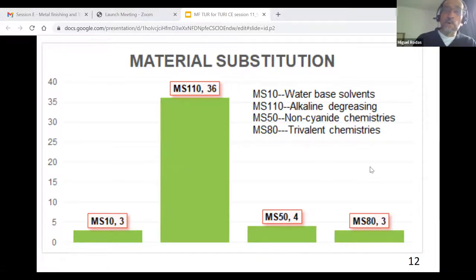And here is what I found on material substitution. 36 facilities are implementing a jump to use water-based alkaline degreasing. So they are no longer using organic solvents, but now they're using alkaline degreasing. MS-10, we find 3 facilities only using water-based solvents, and MS-50 is 4 facilities using non-cyanide chemistries, and the code is the code we use for pollution prevention in the City of Los Angeles. I wanted to mention that across other states, they might use something else, but this is exactly the code we're using in the City of Los Angeles.